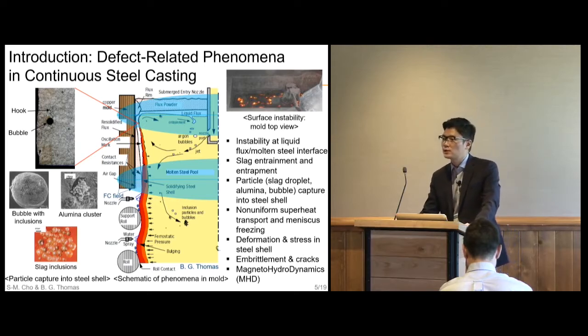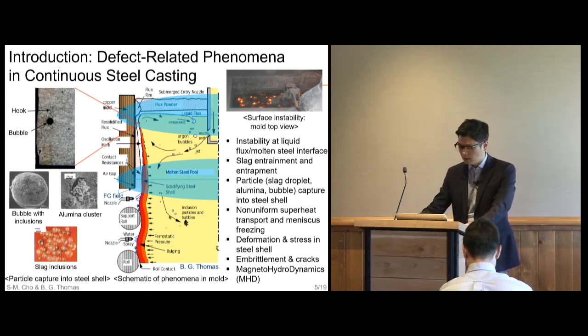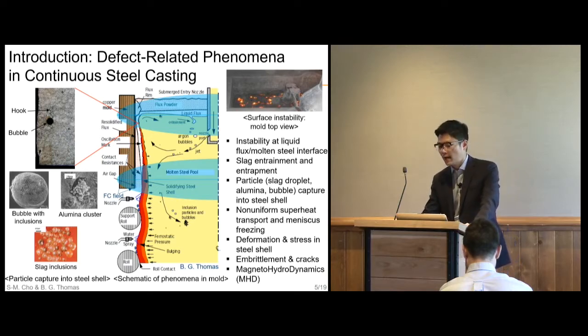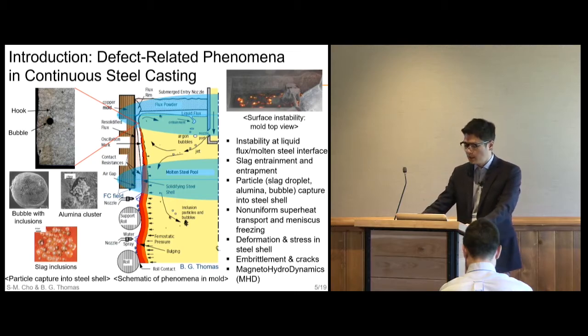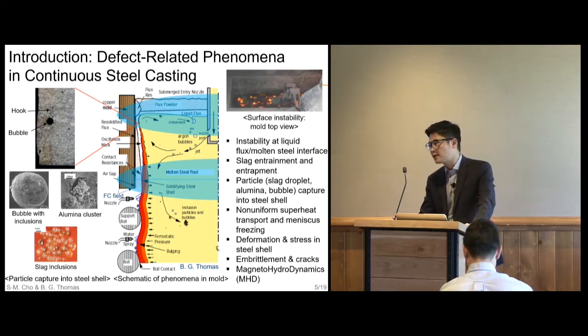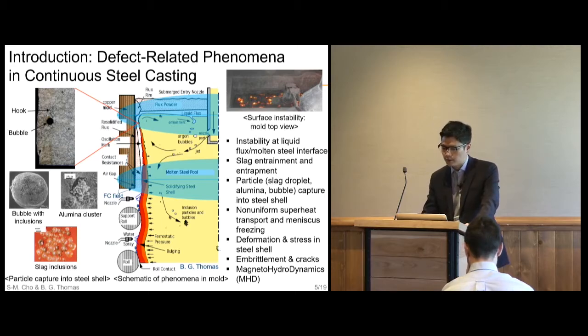Also, argon gas is injected into the molten steel pool to prevent nozzle clogging, but non-optimized casting conditions can make the bubbles and inclusions entrapped by the solidifying steel shell. Another problem, initial solidification defects, may be caused by non-uniform superheat distributions near the solidifying steel shell. And there are depressions and cracks caused by the undesirable thermomechanical behavior of the solidifying shell. But all these defects can be reduced if electromagnetic systems are correctly applied to this system.